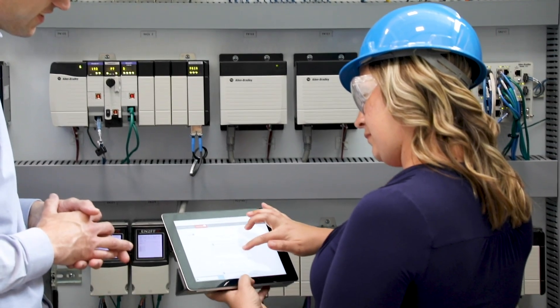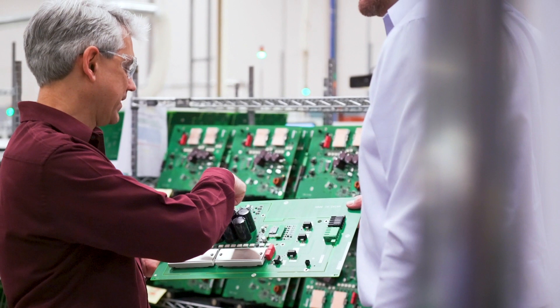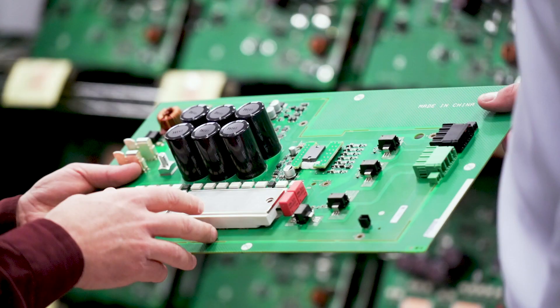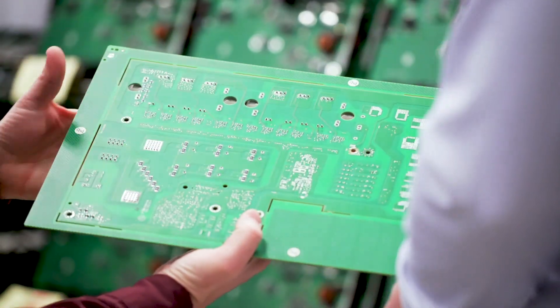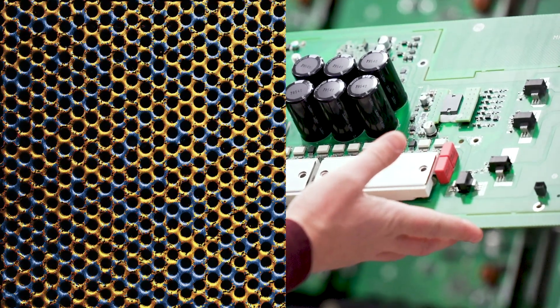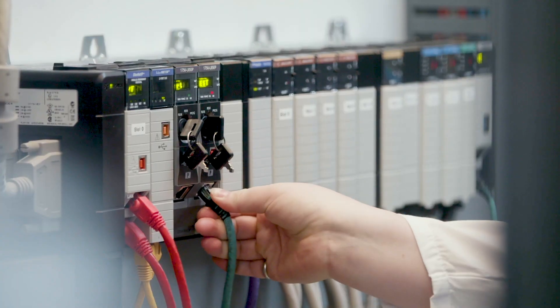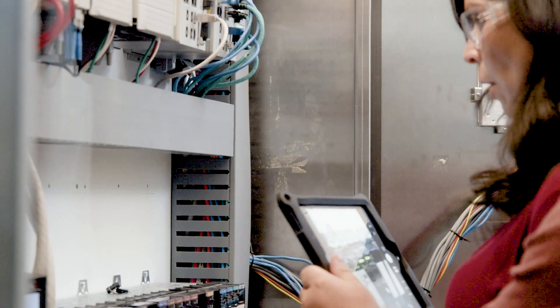Really the main driver was the trend towards miniaturization. When you look at products that were made 20, 30 years ago, they were much larger than what they are today. As you decrease the size of these products and pack more and more technology in there, the spacing between conductors and components inside becomes smaller and smaller. So now the tiniest bit of corrosion can bridge across conductive surfaces and create failures of the components themselves or the product itself.